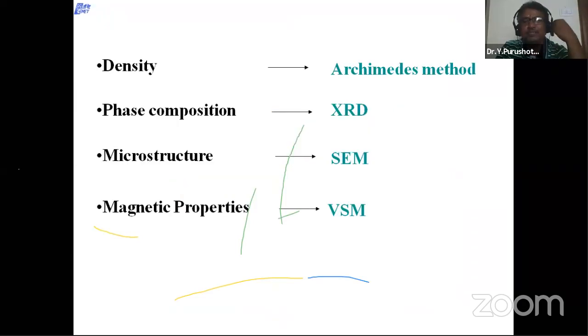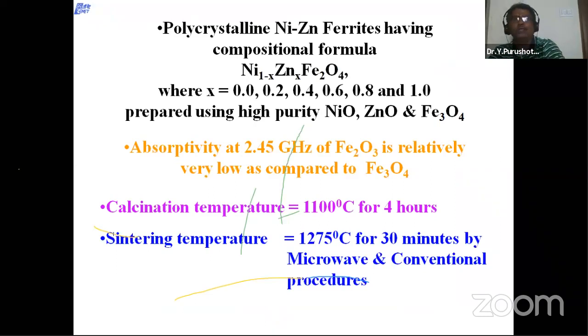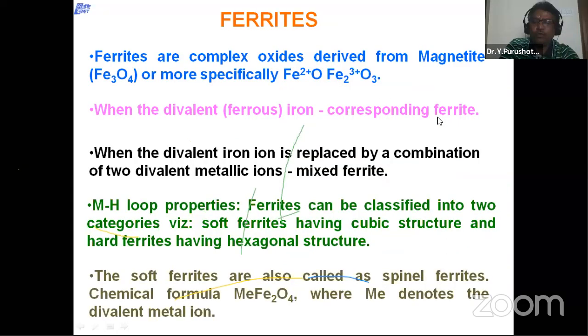After sintering, characterization, which uses very well-known techniques: density by Archimedes method, structural composition by XRD, microstructure by SEM, magnetic properties by vibrating sample magnetometer, VSM. I mentioned nickel zinc ferrites in particular because we studied them in detail. The compositional formula is Ni(1-x)ZnxFe2O4, where x equals 0 to 1 in steps of 0.2. We started with high purity nickel oxide, zinc oxide, and iron oxide. Here we used two batches of iron oxide, Fe2O3 and Fe3O4, because we wanted to see the absorbability of microwaves by Fe2O3 and Fe3O4.